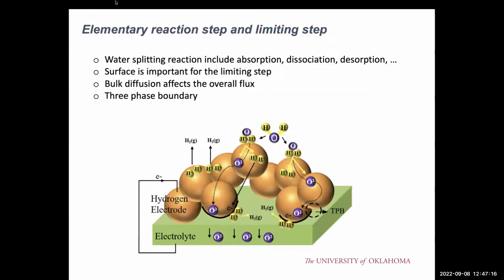Another thing is bulk diffusion. Bulk diffusion means that when you have the proton dissociated, it needs to diffuse from the particles of the electrode, as shown in this figure, through either the surface or the bulk into the interface, into the three-phase boundary between the electrode and electrolyte material. This is another complicated process in the SOC processing.